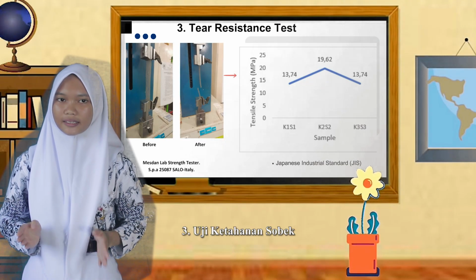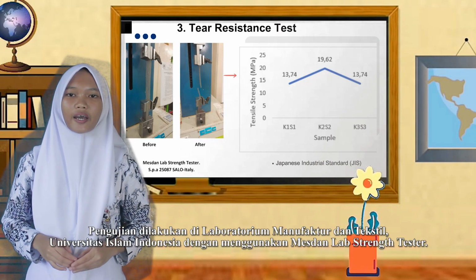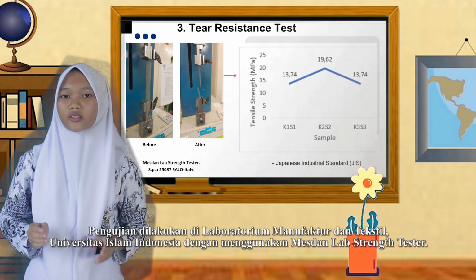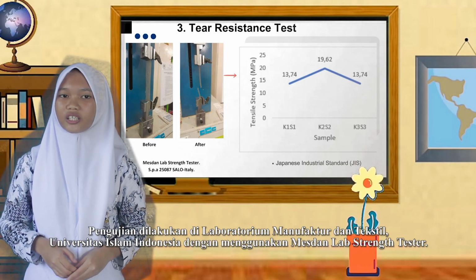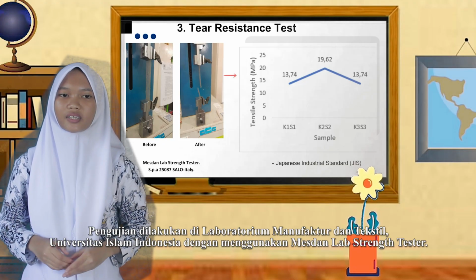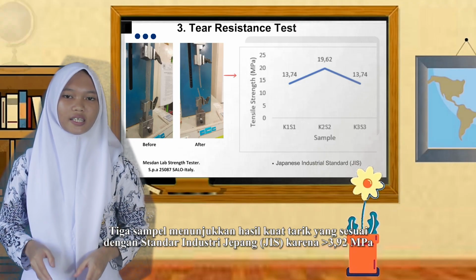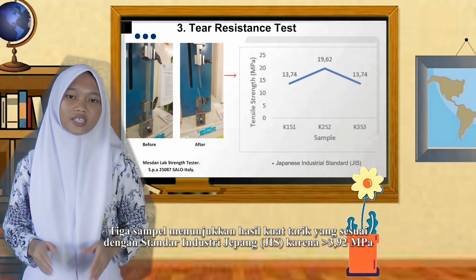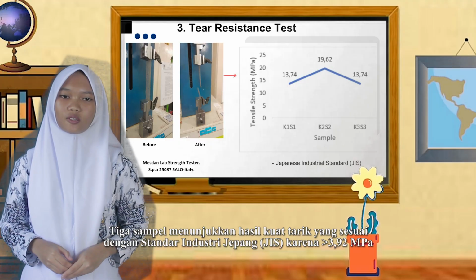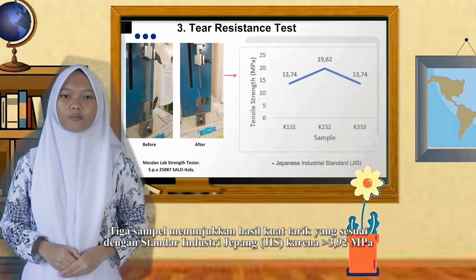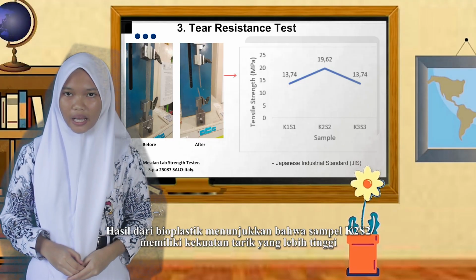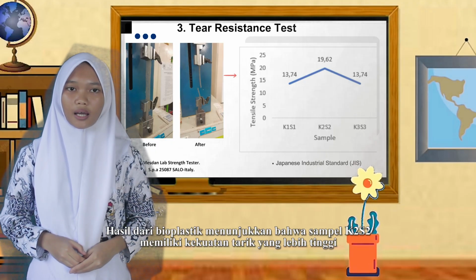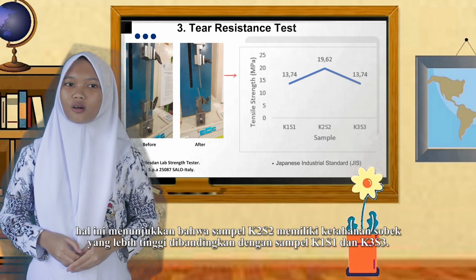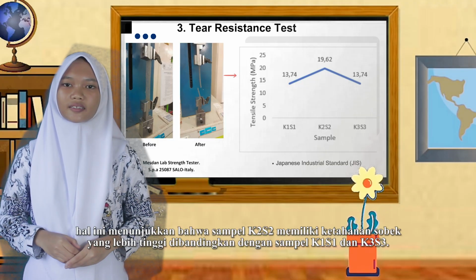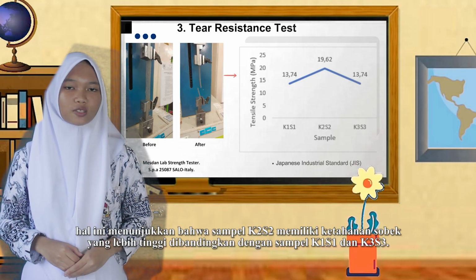Third, tear resistance test. The test was carried out at the Textile Manufacturing Laboratory at the Islamic University of Indonesia using the Mesdan Lab Strength Tester. The 3 samples showed tensile strength results in accordance with the Japanese Industrial Standard because they were more than 3.92 MPa. The results from the bioplastics showed that the K2S2 sample has a higher tensile strength. This showed that sample K2S2 has higher tear resistance compared to the K1S1 and K3S3 samples.